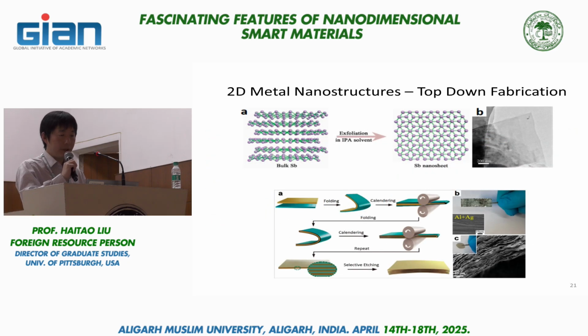There's also a top-down fabrication approach, and some of this can be done using exfoliation. An example here is antimony, because bulk antimony has a layered structure to begin with, so you can use the same kind of exfoliation approach to get single-layer nanosheets of antimony. Again, quite amazing.